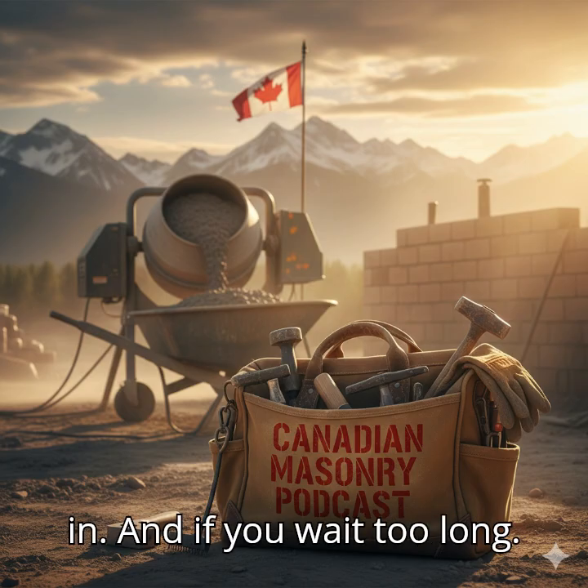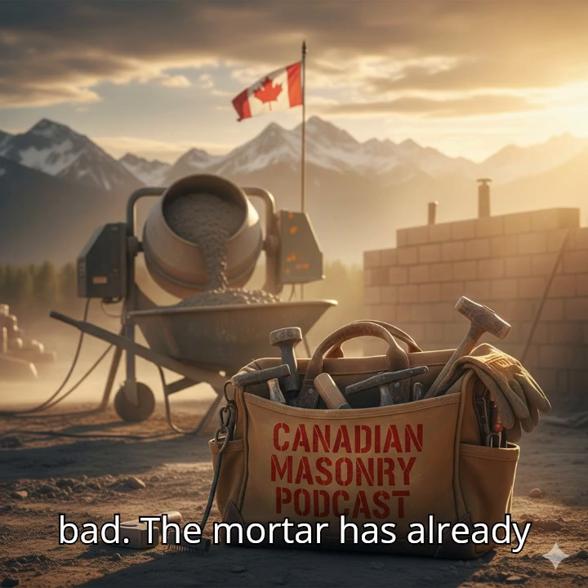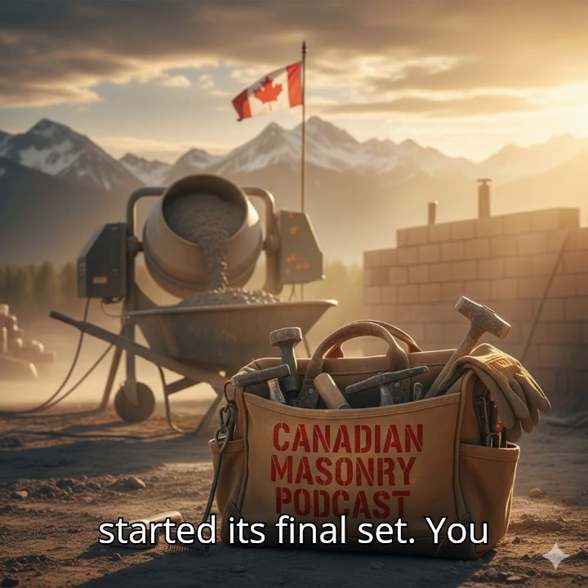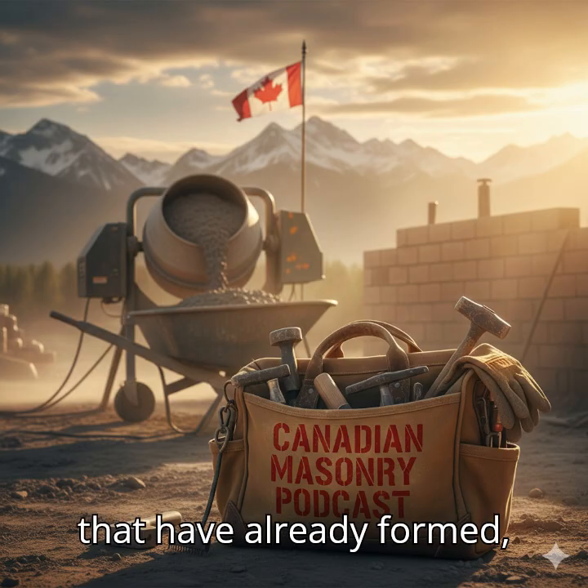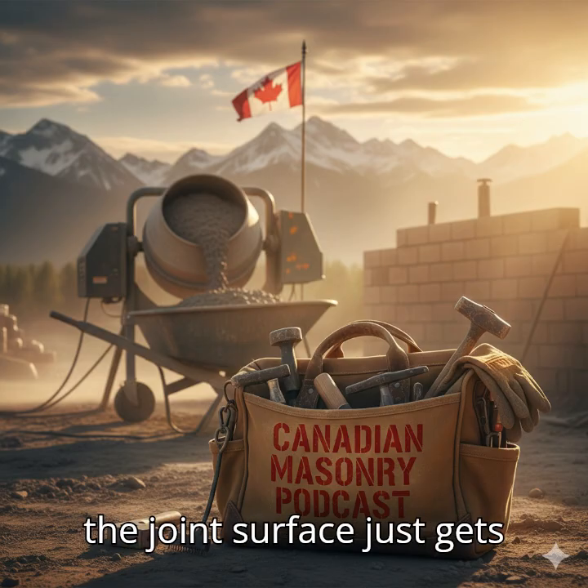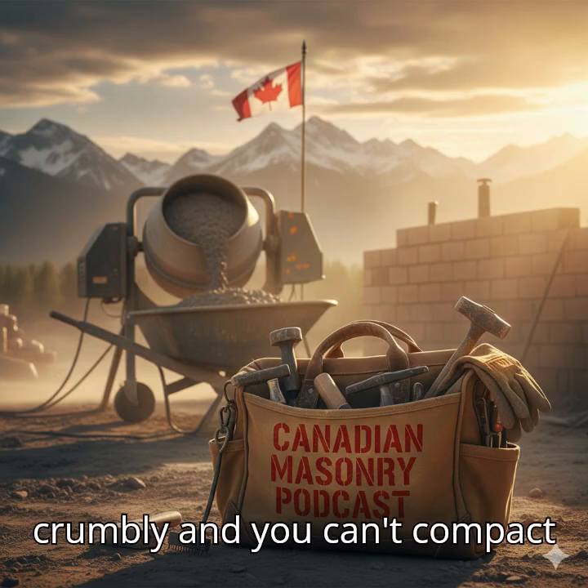And if you wait too long? Tooling too late is just as bad. The mortar has already started its final set. You risk disturbing the bonds that have already formed, creating micro cracks, and the joint surface just gets crumbly, and you can't compact it properly.